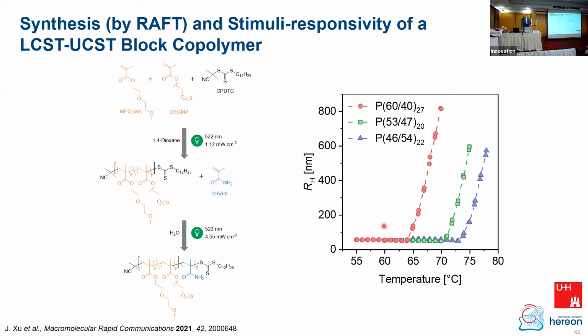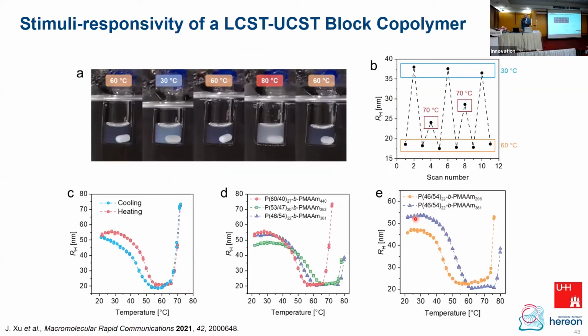And what you get here depends on the composition. This is the first block, the random copolymer of these two ethylene glycol containing comonomers. Depending on the composition, you can adjust the LCST, so this is fine. And when you go for the block copolymer of one of these systems, you can now see a UCST at the lower temperature. You heat up, then the system becomes soluble. So the hydrodynamic radius goes down. We get the unimers, we get the polymers dissolved completely.